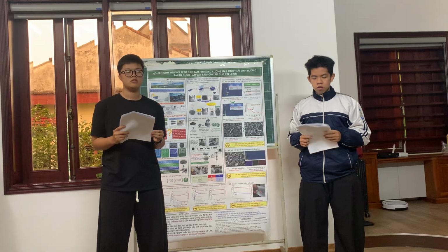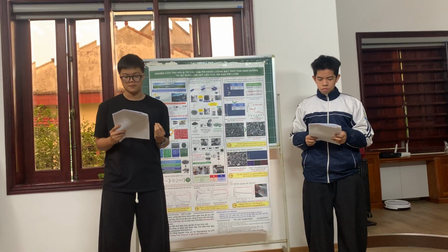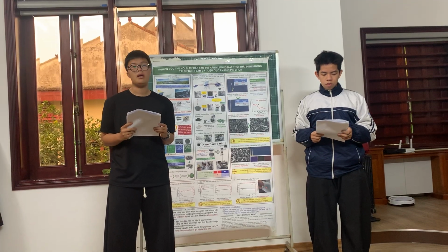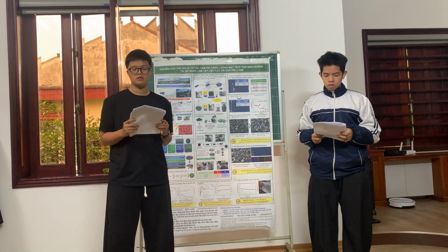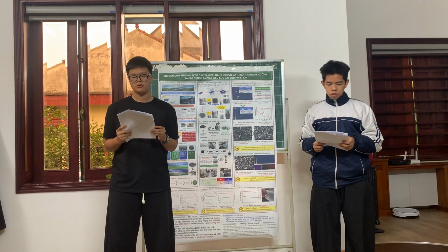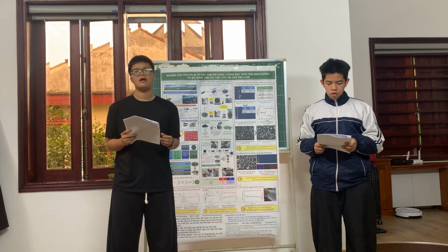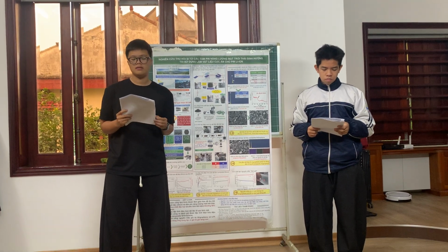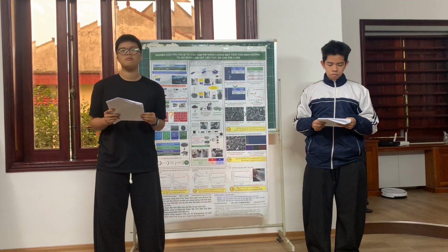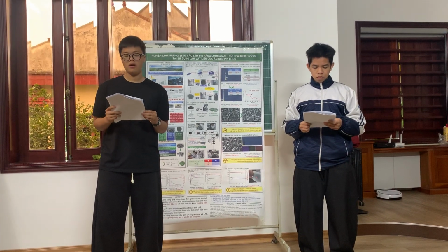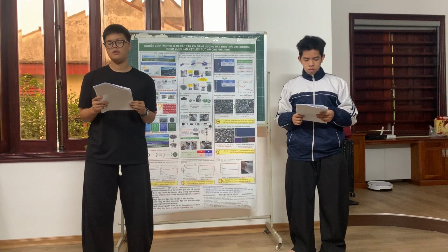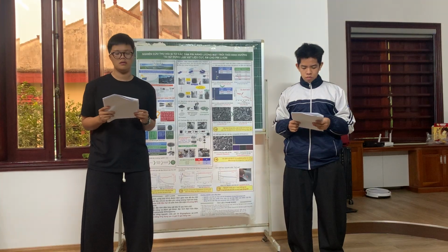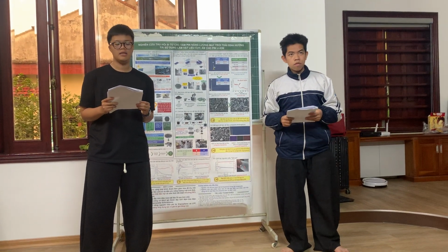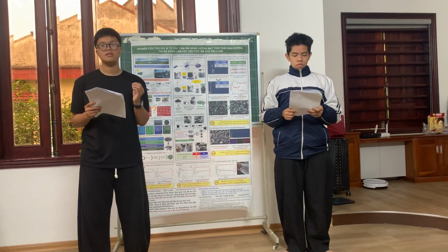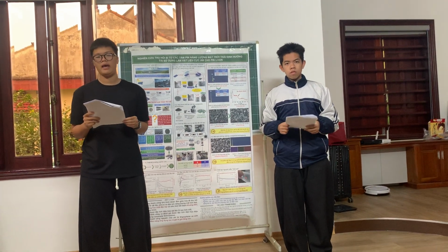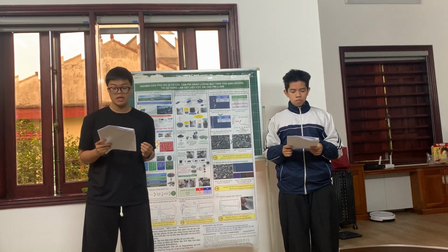In summary, this study successfully achieved its objectives. First, we developed a simple and effective process to recover and refine silicon from end-of-life solar panels, achieving cost savings of at least 50%. Second, we evaluated the electrochemical properties of silicon after refinement. Third, a silicon-graphene composite anode was successfully fabricated, showing significant improvement in stability. And finally, a prototype lithium-ion battery using the silicon-graphene anode and LFP cathode was assembled, demonstrating a strong potential for practical application.